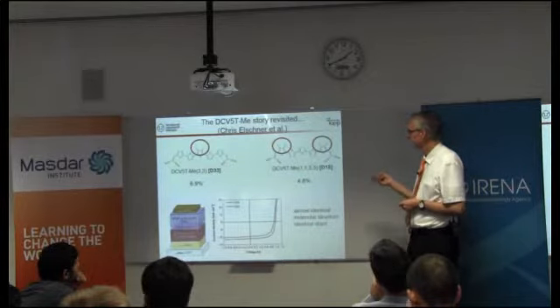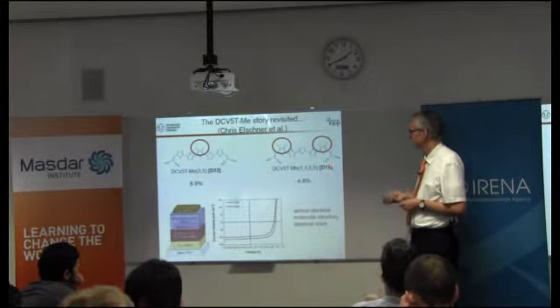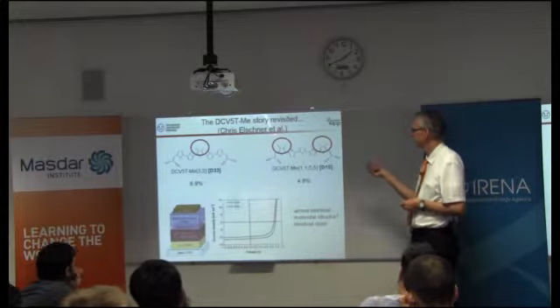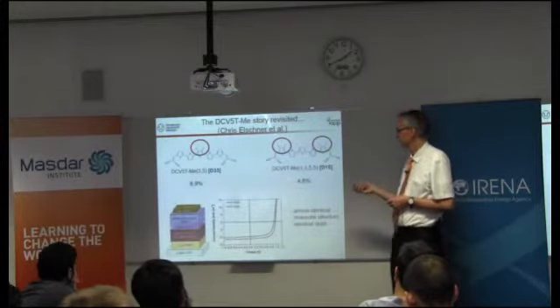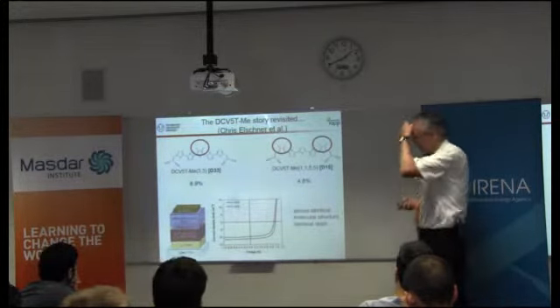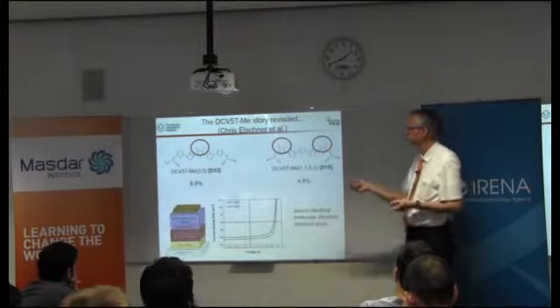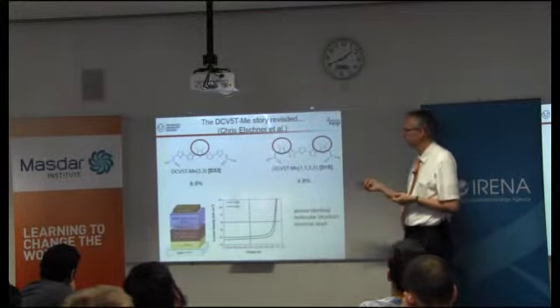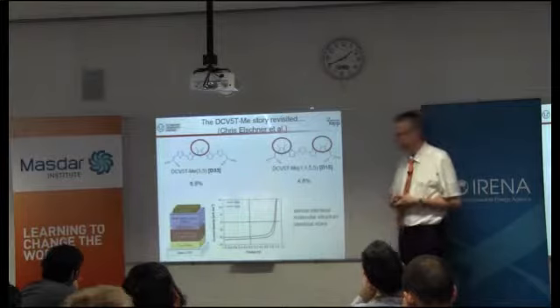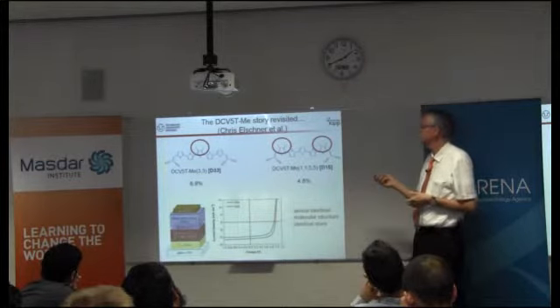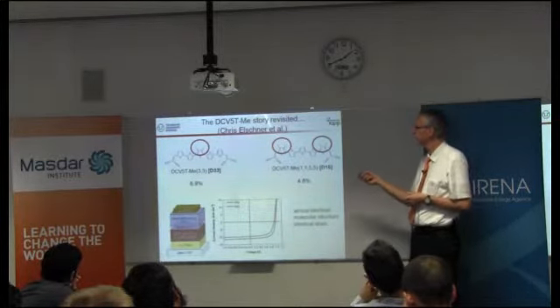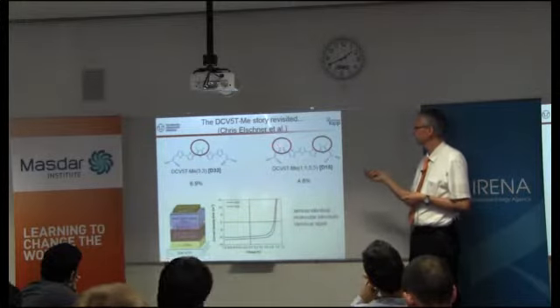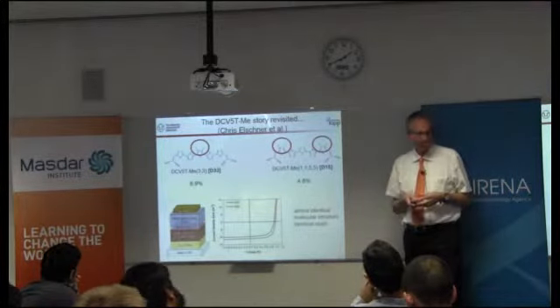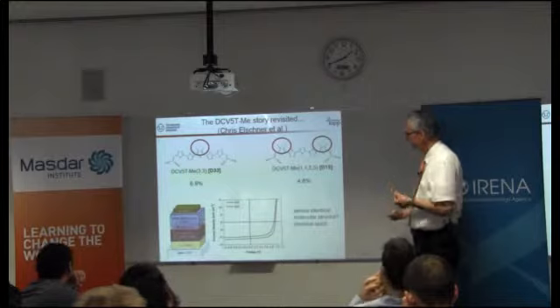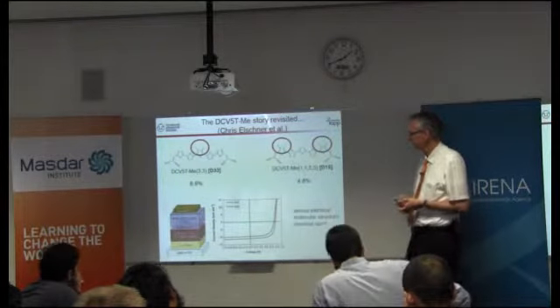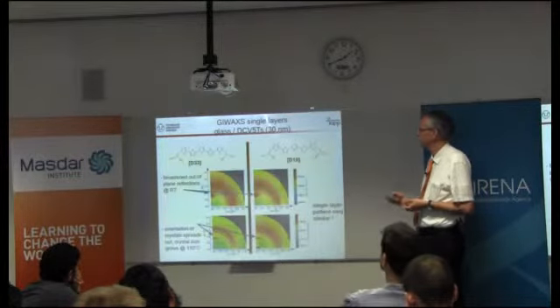And the other compound, the compound 1,5, which has the methyl groups here at the end, was significantly worse, and we published a paper where we showed that this is better, and we argued this is better because it has the better crystal packing. Obviously, these small differences in the molecular structure make a difference in the crystal packing. Now, in the meantime, we've learned that life is more complicated than initially thought.